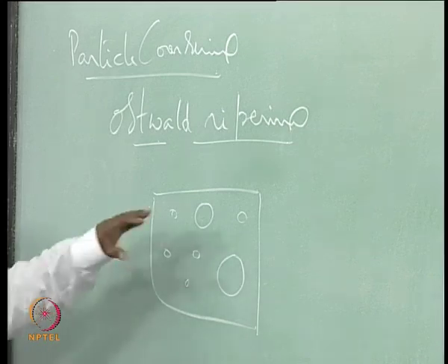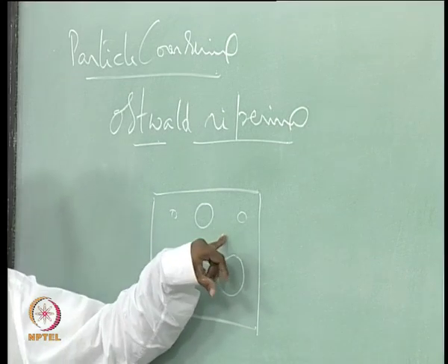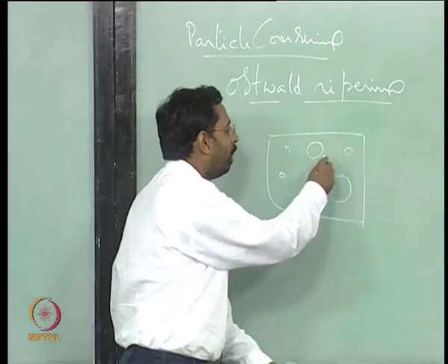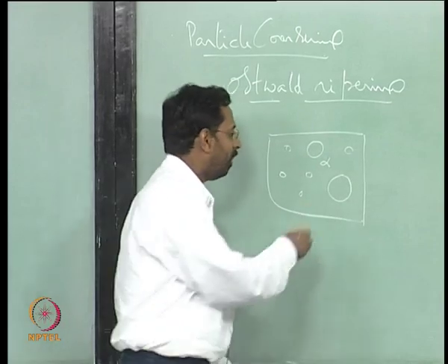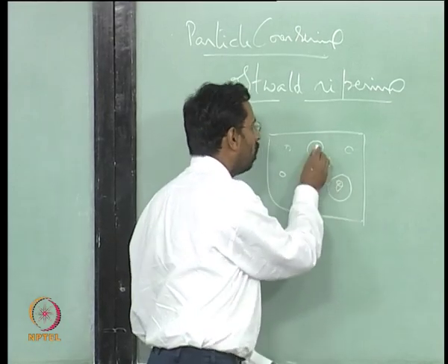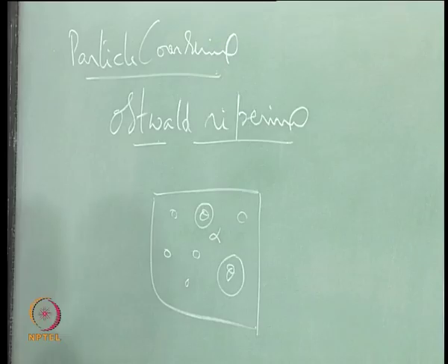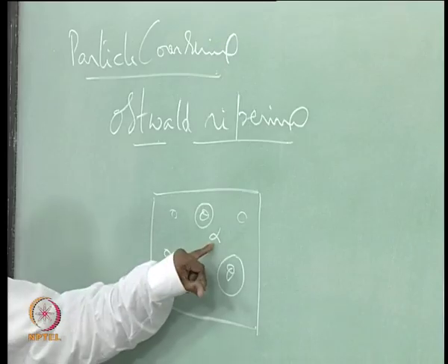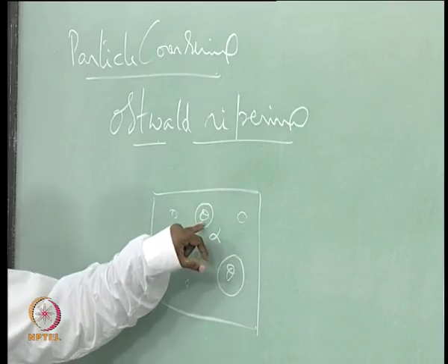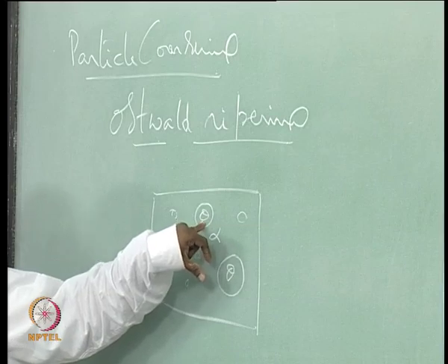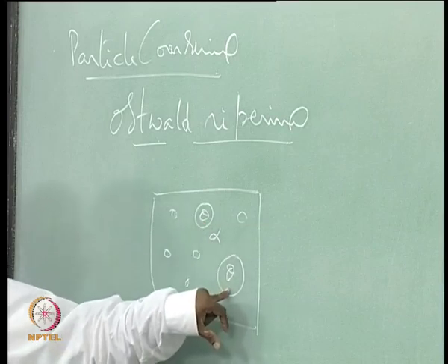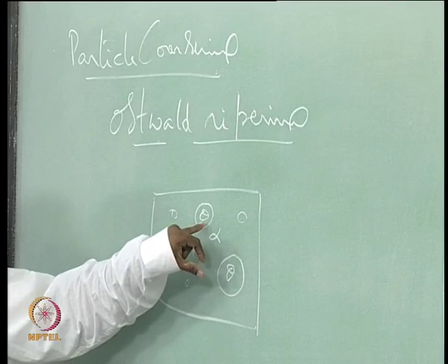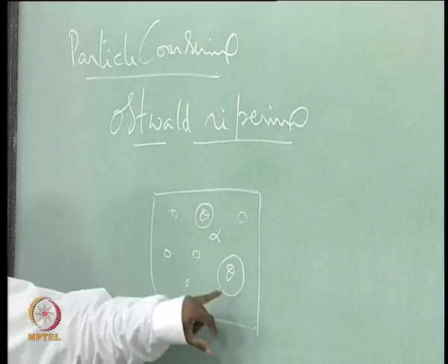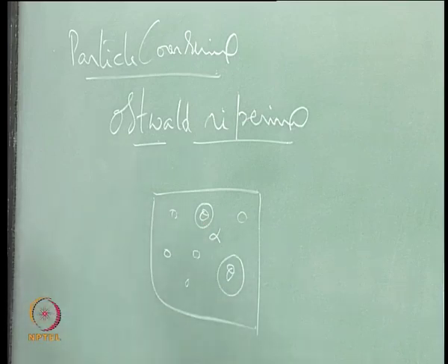I would repeat that the composition of the matrix, which is alpha in our case, and let us say this is theta, whatever precipitate it is. The composition of alpha in equilibrium with this theta, this is also the same theta. The composition of alpha in equilibrium with this theta is different from the composition of alpha in equilibrium with this theta. Why does this happen?